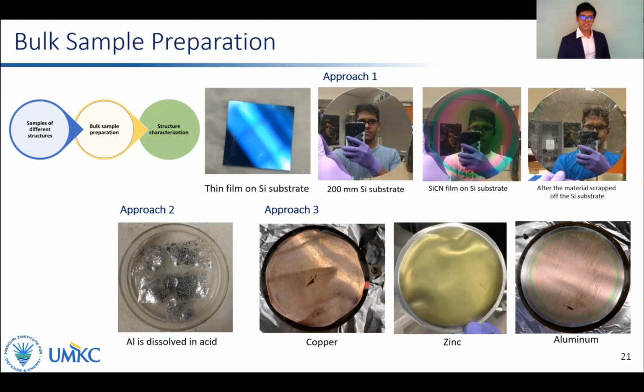Out of these substrates, the copper substrate was found to peel off the films very nicely, and XPS on these powder samples indicated only mild contamination with oxygen.